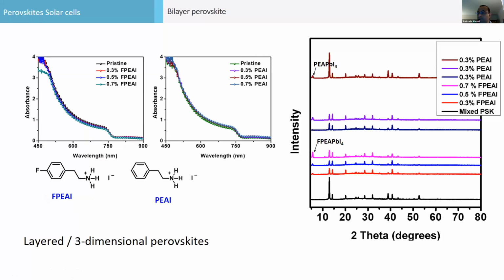Let's talk about now. This was some of the layered three-dimensional perovskite we talked about. Now another term is called layered perovskite. He called them two-dimensional perovskite, but I call them layered perovskite. They were the pioneer in this field. So what we took is you can take some fluorophenethyl ammonium molecule, fluorophenethyl ammonium iodide, because they will not form a three-dimensional structure, and they will form a layered perovskite. So what we call is a bilayer type of perovskites.